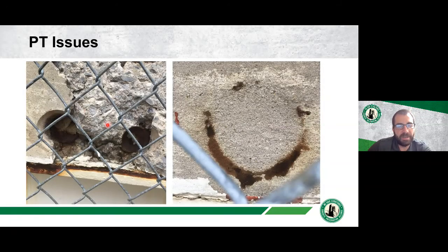Here's the anchorages of the tendons, and you can see obviously there's a concrete spall here. The anchorage caps are gone. This allows the strand to have moisture and exposure here. Here is an anchorage, and you can see moisture transport through the anchorage. So obviously we have moisture and grease coming out of there, so that's an indication that there's water along those tendons.